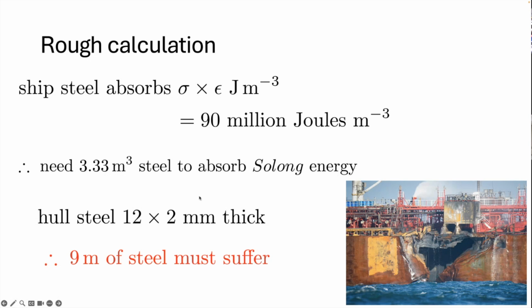And the thickness of the hull steel is 12 times 2, I'll explain the 2 later on, millimeters. And therefore, a very easy calculation tells you that about 9 meters of steel must suffer, and that's approximately the scale of this gash in the side of the ship. So steel is incredibly important in its ability to absorb energy during deformation.